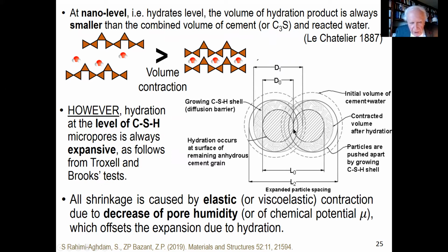What develops here is something like crystal growth pressure. It's actually exactly analogous. That pushes the attached particles apart, but resisted by the skeleton elastically or viscoelastically. And that's actually the expansion, because these shells cannot be accommodated freely, and the growth causes expansion, and obviously as long as the diffusion goes, it goes for a century and more. So the conclusion is all the shrinkage is elastic, actually viscoelastic, possibly because the viscoelasticity even at this nanoscale is somewhat debatable, because these are actually crystals. And it is due to decrease of pore humidity.